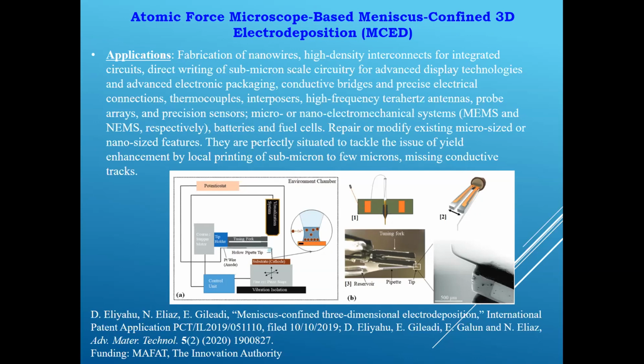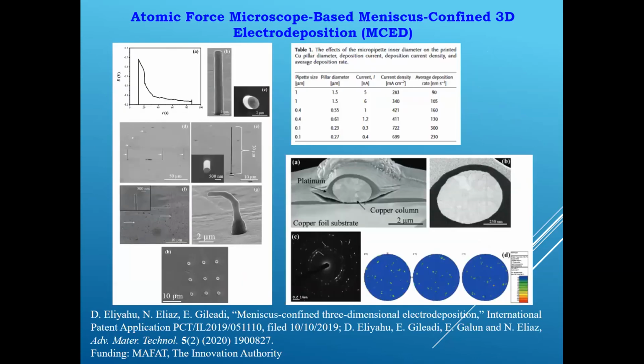the tuning fork. The quartz crystal tuning fork provides resonance control, and I don't have time to show the difference in results that we obtained, but QTF gave us eventually the best results. Using this scheme, three-dimensional printing of high quality, fully dense, uniform, and exceptionally smooth freestanding straight and overhang pure polycrystalline copper pillars with diameters ranging from 1.5 micron to 250 nanometers, and an aspect ratio higher than 100 was demonstrated.